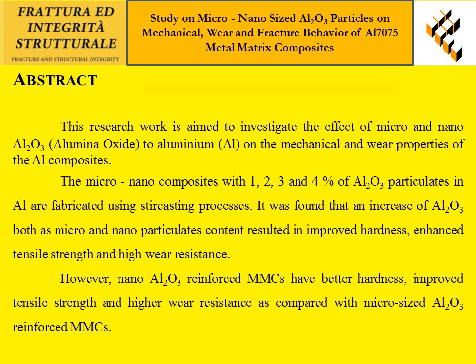The micro-nano composites with 1, 2, 3 and 4 percent of aluminum oxide were used to fabricate the aluminum composite using the stir casting process. It is observed that increasing the Al2O3 particulate content in both micro and nano sizes results in improved mechanical properties and high wear resistance. However, nano-sized Al2O3 reinforced composites show better strength and higher wear resistance compared to micro-sized Al2O3 reinforced composites.